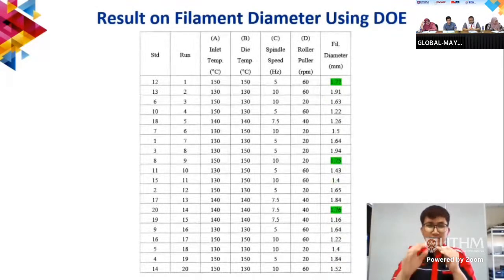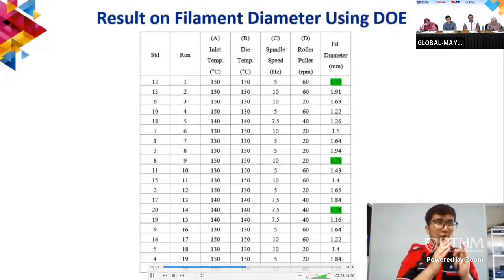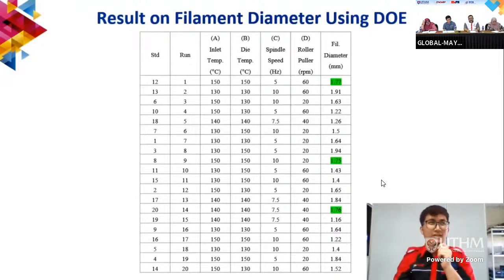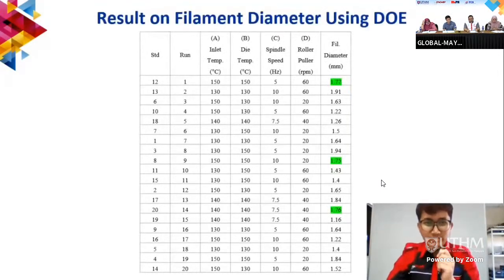For the result on filament using Design of Experiments, we ran 20 runs, and we got this output, which has 3 of the runs that reach around 1.75 to 1.80 millimeters. For your information, for FDM filament we must have a diameter of around 1.75 to 1.80 millimeters to create an accurate filament for an FDM 3D printer. On this result, we can see that three outputs are in the 1.75 to 1.80 mm range.